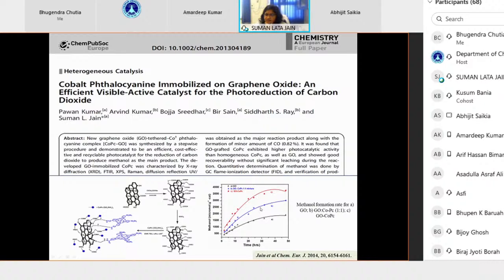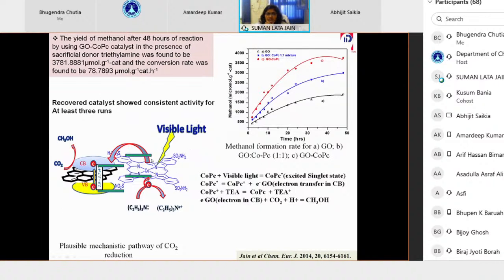This difference in reactivity also confirms that chemical attachment between the two components not only enhances the stability of the molecule but also has a positive effect on the conversion and the selectivity of the product. We selectively got methanol in this reaction, with a significantly higher yield in comparison to several literature reports. So how does this system work? Clearly we can see how effectively this system works compared to its components. So this is the basic mechanism.